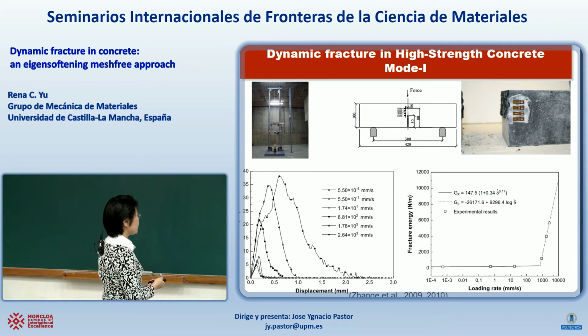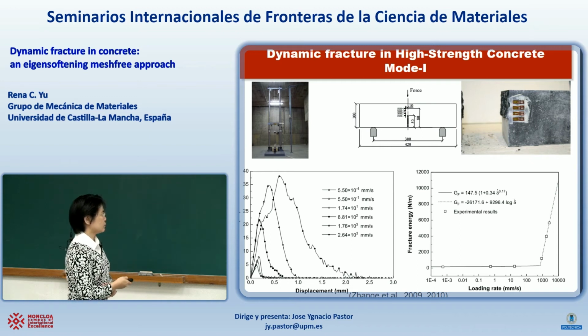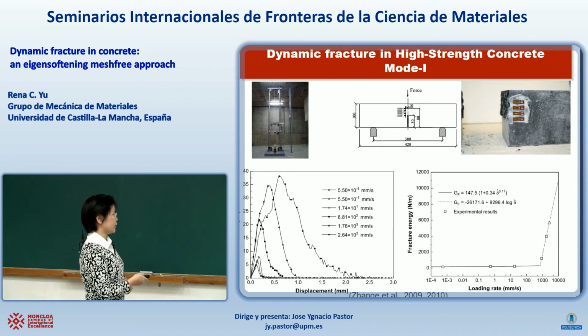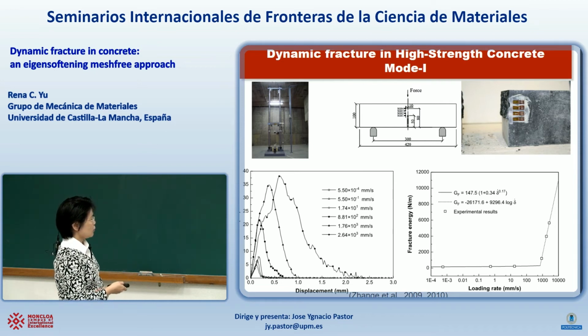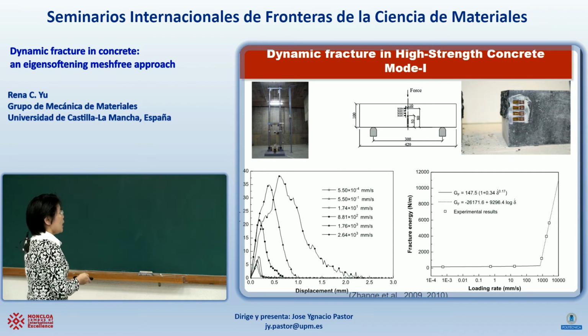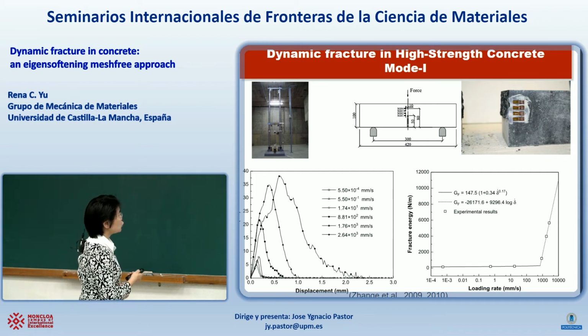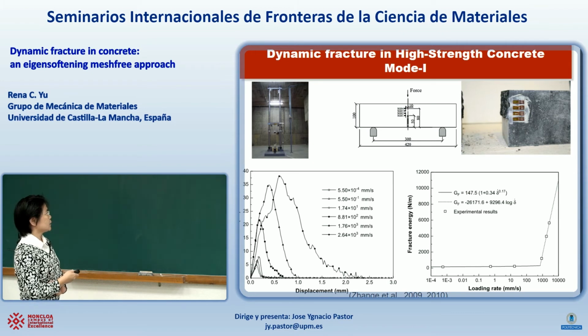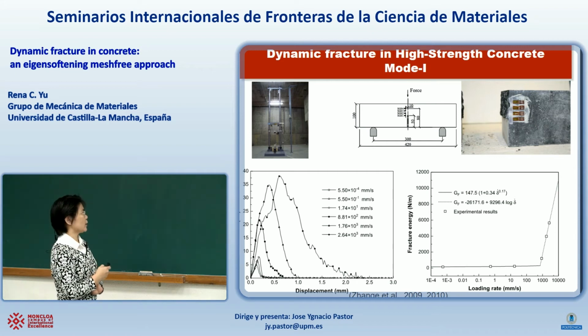Okay, and if we integrate the area below the reaction load and the displacement, we have what is called fracture energy. I will say it's a kind of energy, because it's load and displacement, and we see that at high velocities it increases significantly. And since we want to model those tests, and remember the drop weight was like 120 kilograms, we would like to model both the projectile and the target, which is the beam. So we need our contact algorithm.